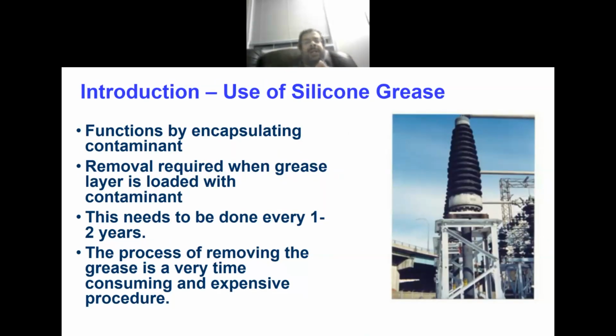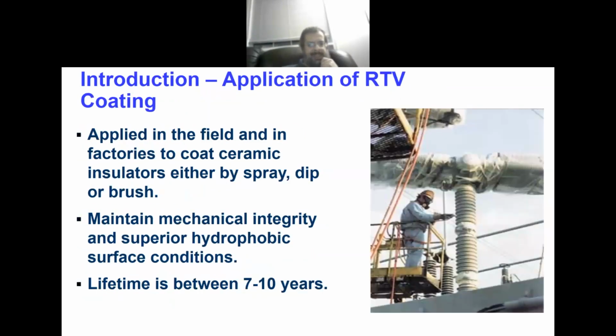Then people came up with another solution, which is to use a sort of grease to cover the ceramic insulators, and they used some materials. The last one they use is silicone grease. Now, the silicone grease will encapsulate the pollutant and prevent the flashover, which is a perfect thing. However, people started to realize that you need to replace the material after 1 or 2 years. And imagine removing those grease materials from the insulators, and we have millions of those insulators. So how tedious is the job? So that's on the short term a good solution, but for the long term it is not a good solution. Next, please.